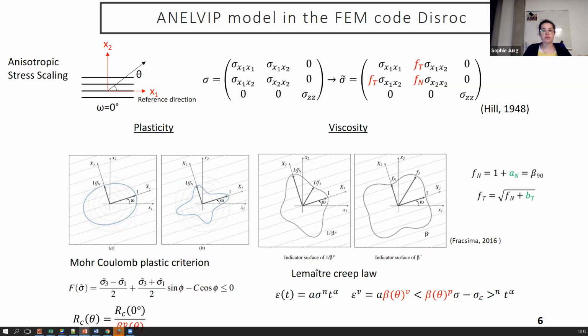So basically for isotropic material, the parameters Fn and Ft are equal to 1, and the figure represented here would be a circle. Then if you change the value of Fn, you describe a change in the behavior in the direction perpendicular to the reference direction. So here you have one direction of reference, and by changing the value of Fn, you change the behavior in that direction. And so the circle becomes an ellipse, and Ft describes the behavior in shear. So the ellipse becomes a kind of star, which can be minimum or maximum at 45 degrees.